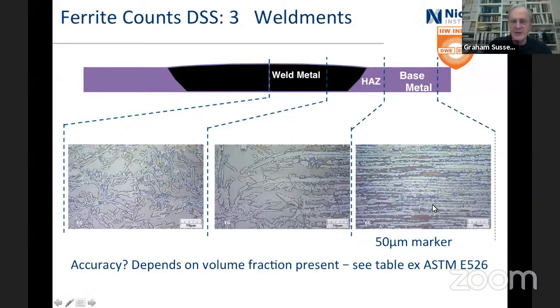This is the parent material, here is the heat affected zone, and here is the actual weld. And imagine trying to do measurements on those at the same level, because one of the things that you've got to make sure of is that you don't have too many of your measurement points in blank.